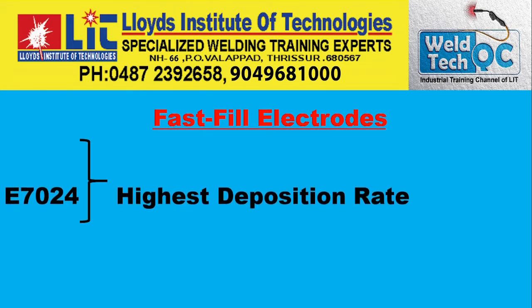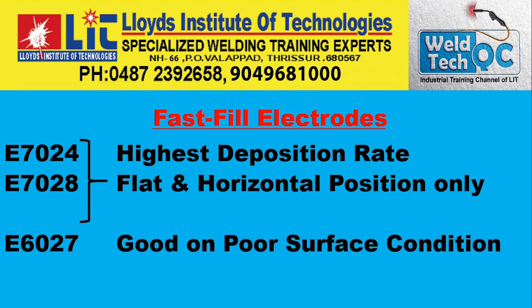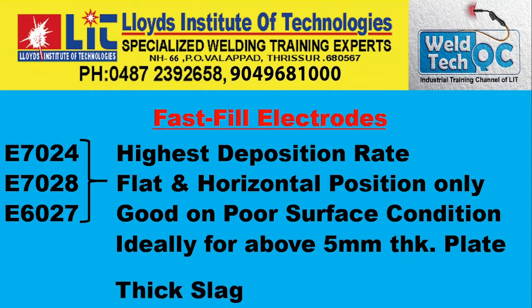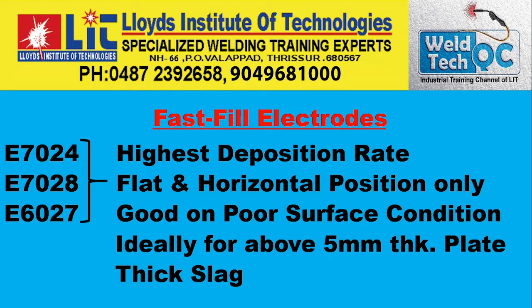Let us see what the AWS classifications for this are. E7024, E7028, E6027. These are considered fast fill electrodes. Highest deposition rate, flat and horizontal position only, good on poor surface conditions, meaning some joints or material surfaces may be very poor, rusty, or a little corroded. In such cases, this will be highly suitable. Mainly this is for thicker plates, above 5 mm thick, and it will have a thicker slag.